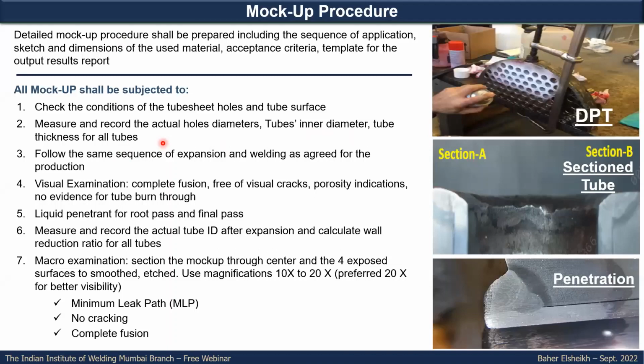Then follow the sequence of the expansion and the welding as agreed in the production. We said that you might do expansion first, then welding, or whatever agreed, you have to apply. Then do the visual examination. You have to see complete fusion, free of visual cracks and porosity indications. There is no evidence of tube burn through. And then apply liquid penetrant, and it is highly advised to apply it for the root pass and again for the final pass. You need to measure and record the actual tube ID after the expansion to calculate how much reduction.